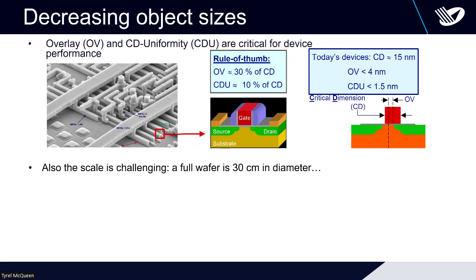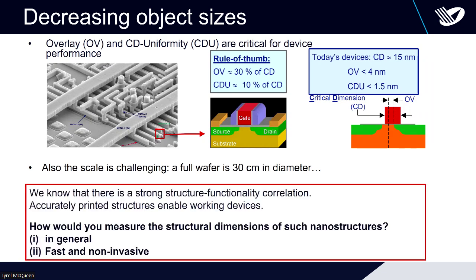And the typical dimensions we're talking about is that the overlay error that we allow to have is 30% of the critical dimension, and the critical dimension error is only 10% of that. That means the critical dimensions have to be printed with 1.5 nanometer accuracy and the overlay with 4 nanometer. So at 1.5 nanometer, this is, I think, then already less than 10 silicon atoms. And again, what we already said, all that on 12 inches. Insane requirements. How would you do that?